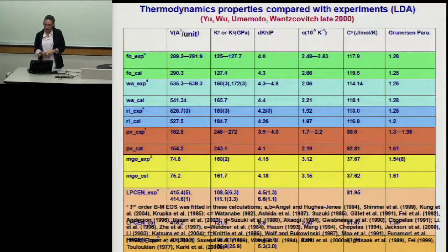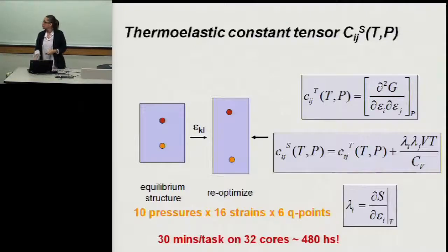very accurately. And we have studied the thermal properties of the major end members, magnesium end members in the mantle. And we conclude that the local density approximation plus quasi-harmonic approximation reproduces very well the properties, primarily the thermal properties. Now, the elastic constants at high temperatures, the way we do them, and that gives us these elastic constants in